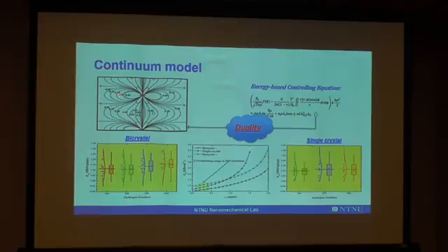If a dislocation is emitted here, it will be attracted by the grain boundary, and if it's emitted here, there will be a repulsive interaction between the grain boundary and dislocation. And this figure explains why we use a specific sign here, and thus this is the duality caused by the grain boundary.